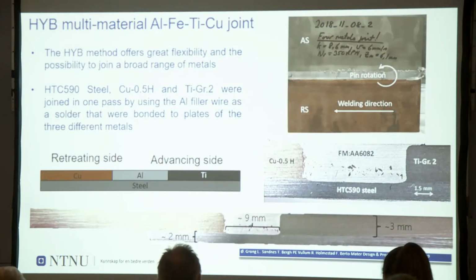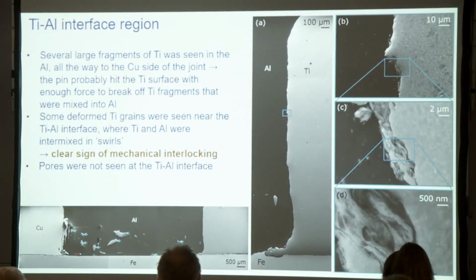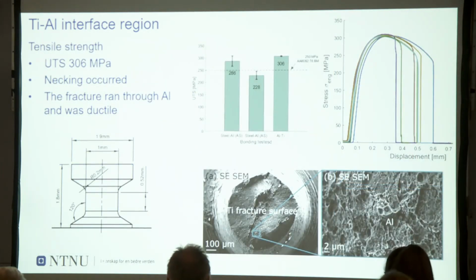This has been applied also to multi-material weldings, aluminum, steel, titanium, copper, welded together in one single pass. And I will only focus on the titanium aluminum interface, where again you can find clear signs of mechanical interlocking, which is a geometrical effect that is able to improve the loading capacity of these weldments. And in fact, if you study the static properties at the welded lines, we find highly repeatable results with high strength of the bonding in the bonded condition.